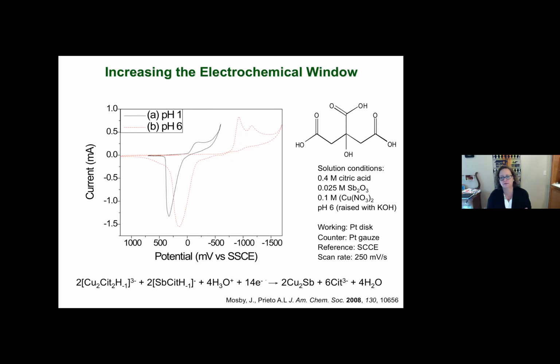Remember, I asked that we use as low toxicity chemicals as possible. Antimony we can't avoid because it is part of the anode, but citric acid is actually just a really common food preservative. It's soluble at really high concentrations, and the carboxylic acid groups deprotonate at different pHs, so they bind pretty strongly to the copper and the antimony, and this is important for the direct electrodeposition.